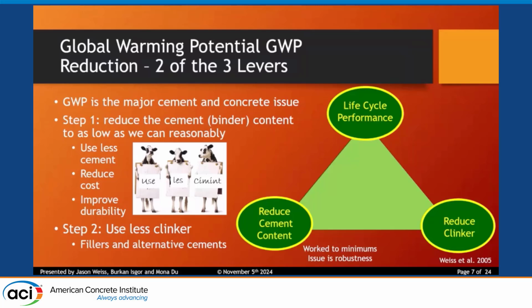If we start putting out materials with a low global warming potential on the A1 to A3 LCA analysis, and we don't provide long-term durability, this is going to be a big problem for the industry. There have already been materials that have been demonstrated that they're getting 3 or 4 years before they're having to be replaced. And that's not good when the agency is requiring or expecting a 50 to 75-year life.